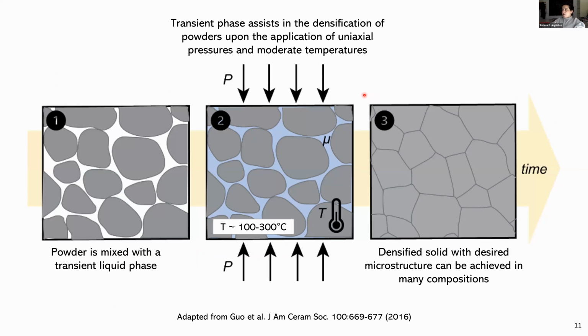I assume for most of you, cold sintering is probably not something you're nearly as familiar with as you are with ultrasound. So I thought it was important to start with a little bit of a crash course on what I mean by cold sintering. Cold sintering, like other sintering processes, is essentially a process to apply pressure to bring particles together and solidify into a material. The main difference is that if you think about the sintering of a ceramic, more than likely you would have to deal with temperatures in the 1,000 degrees Celsius range and pretty high pressures.